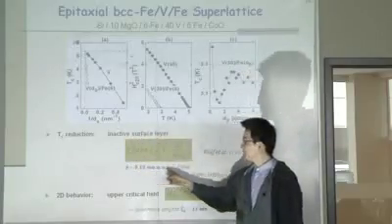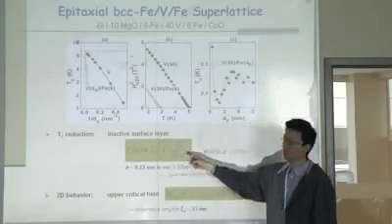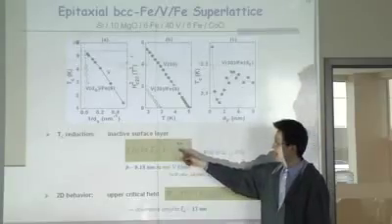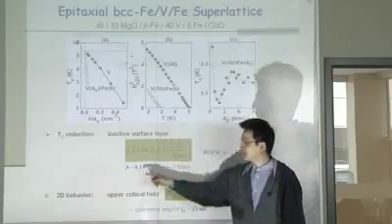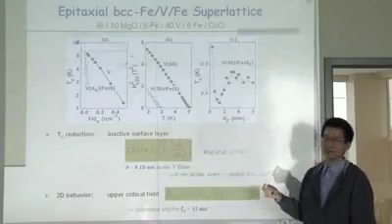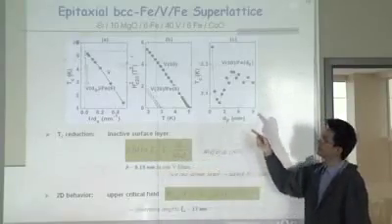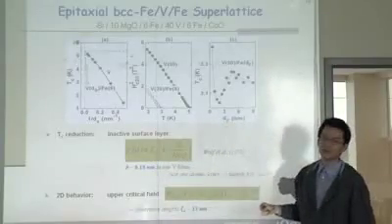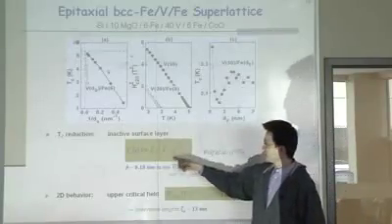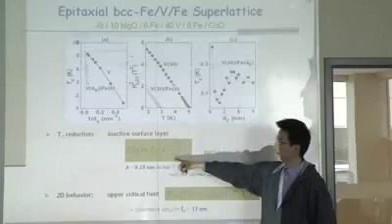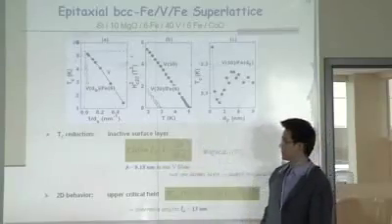Now it follows a simple equation. The Tc is inversely proportional to the thickness, and the inactive layer thickness B we can deduce from the slope, and it turns out to be 0.18 nanometer. This is just one atomic layer. That means the vanadium film we fabricated this way has extremely high quality. The other parameters are the electron density and the coupling energy. So these are constants. Okay.